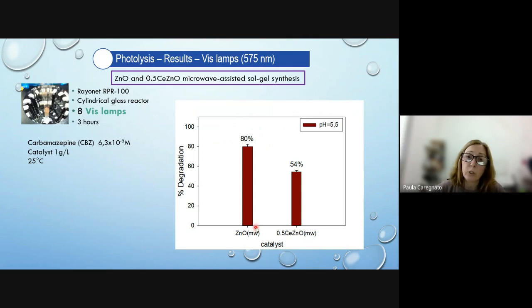Okay, I'm going to show you now our photolysis results with the materials obtained with microwave-assisted Sol-Gel synthesis. With 8 visible lamps, here we can see the percentage of degradation of carbamazepine with both catalysts. We studied it after 3 hours, always after 3 hours of photolysis.